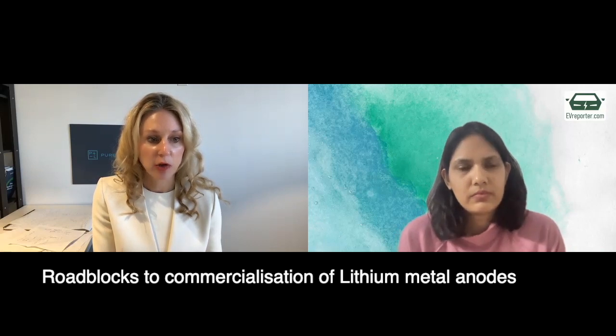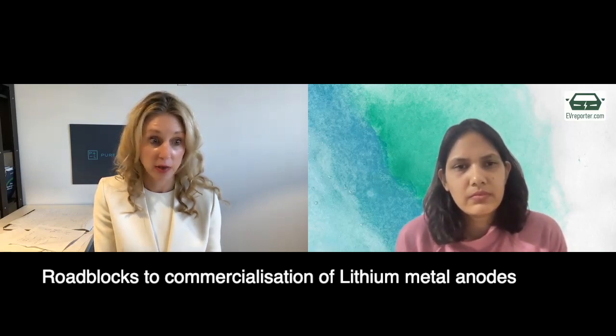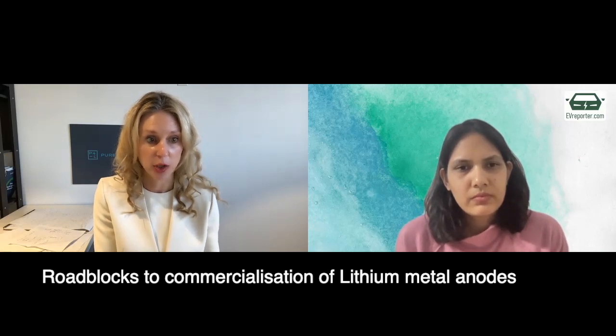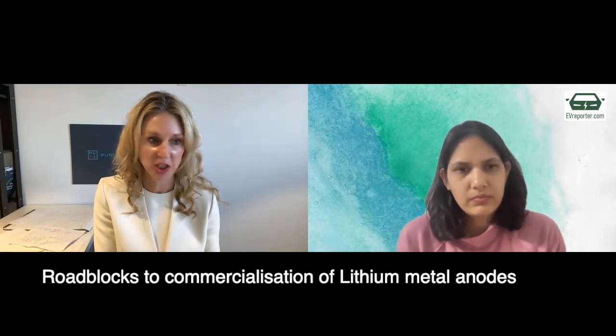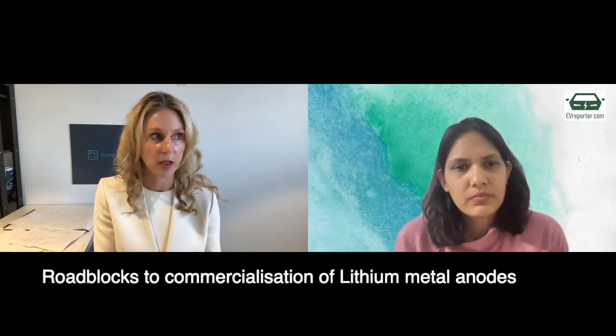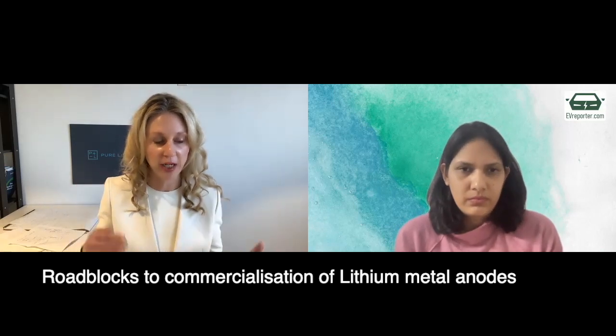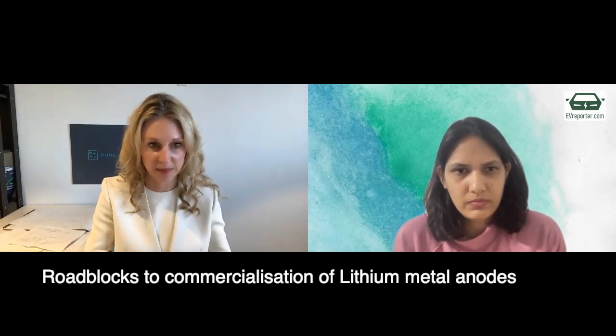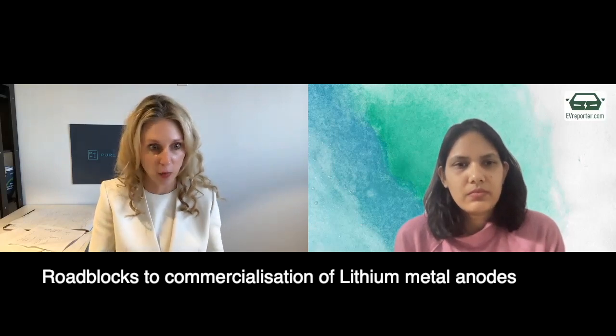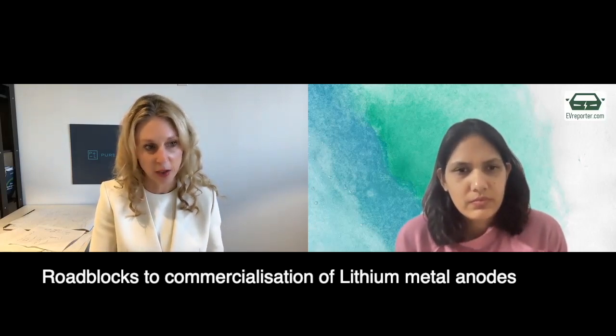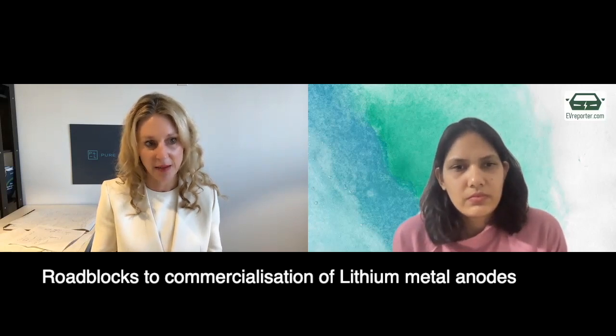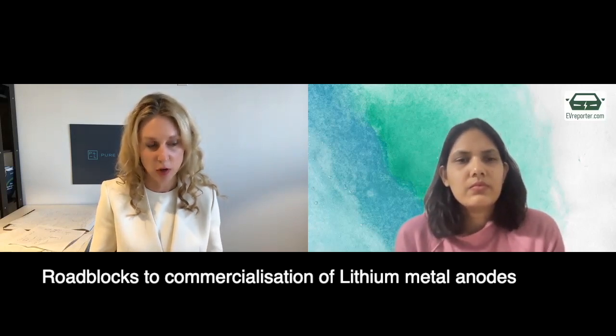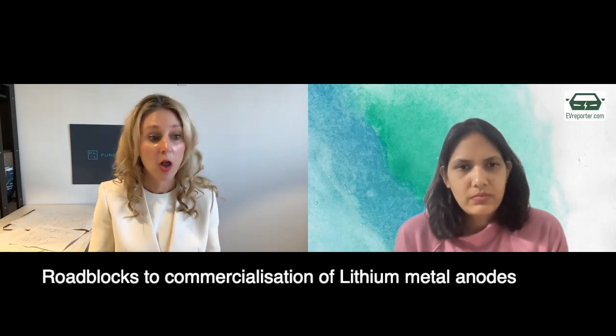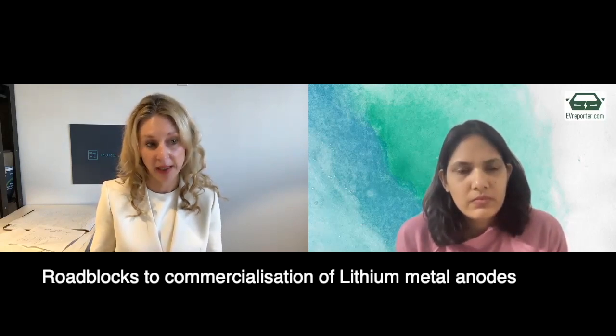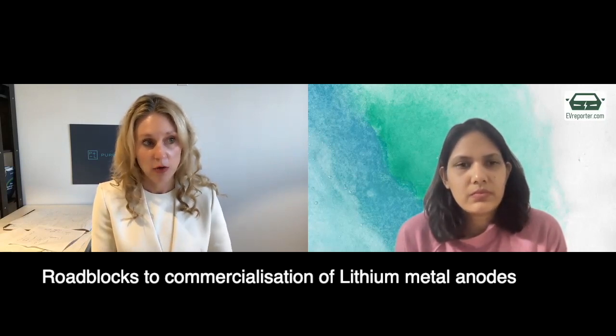The other challenge of utilizing the capacity is the cathodes. The cathodes we use today, the positive electrode, they are highly optimized for lithium ion intercalation chemistry. So imagine a parking garage. And imagine that the cobalt basically are the beams that hold it up, and the lithium drives in and out and finds its spot, and it can only go so fast in and out of the garage. It's limited by diffusion rate. So in order to really utilize a lithium metal anode, you need to have a conversion cathode like a sulfur or a higher rate capability cathode. So those are the challenges.